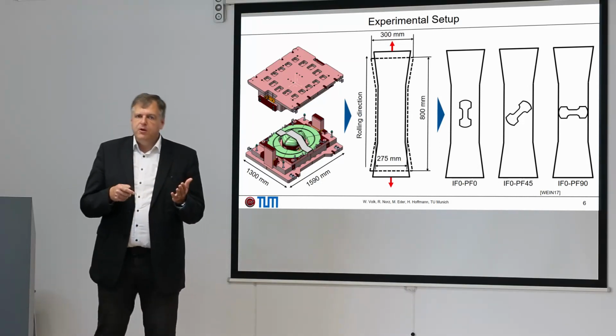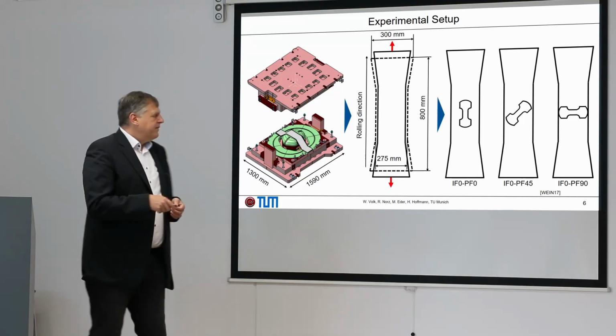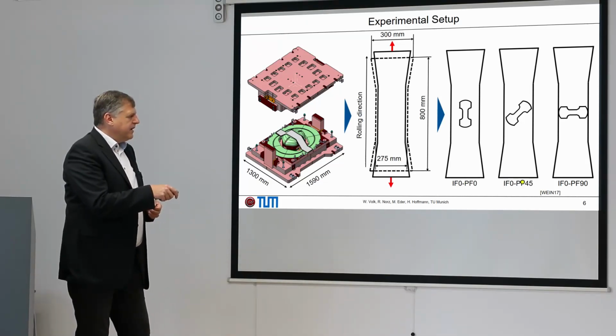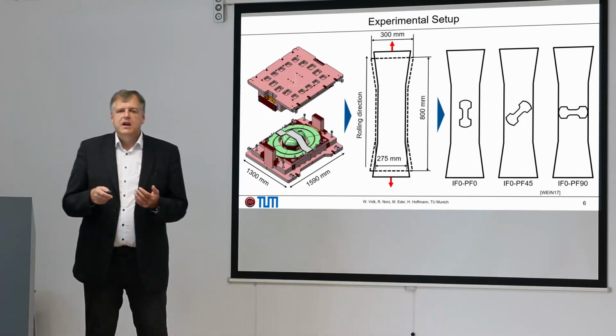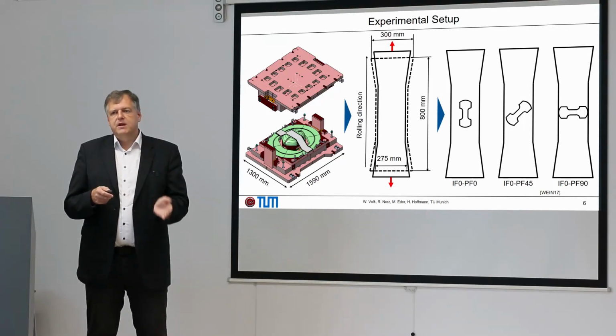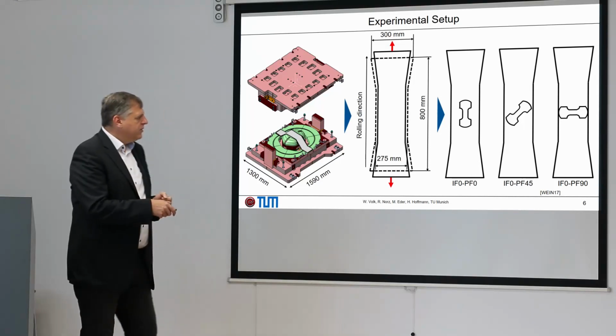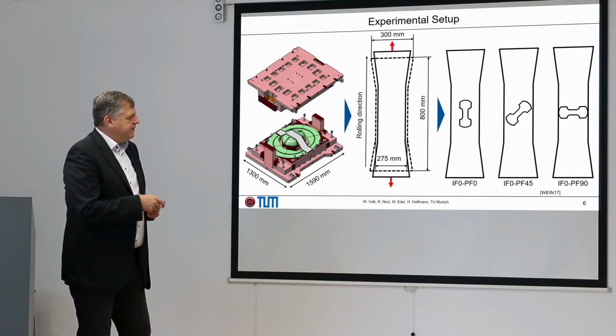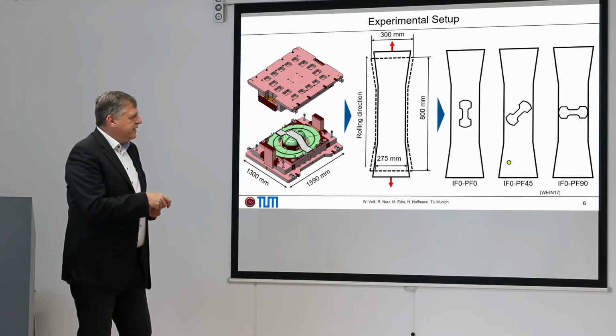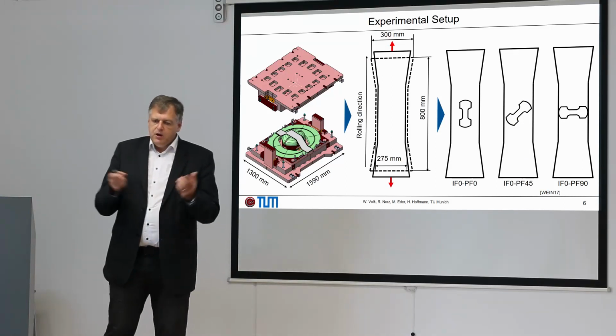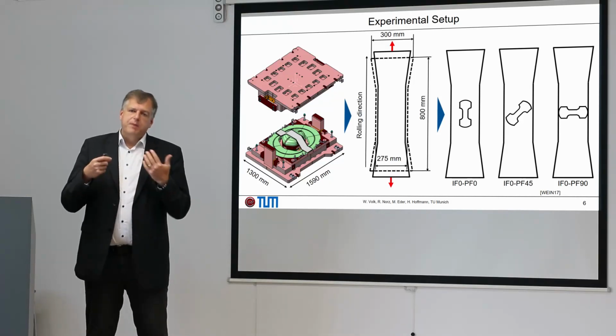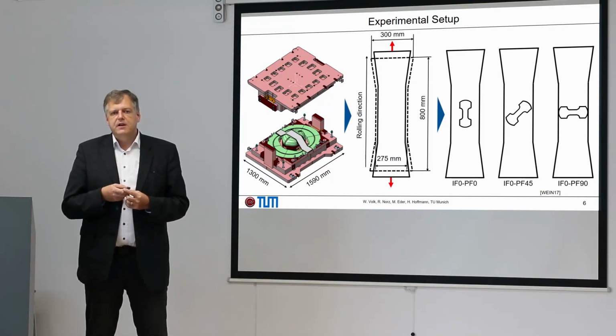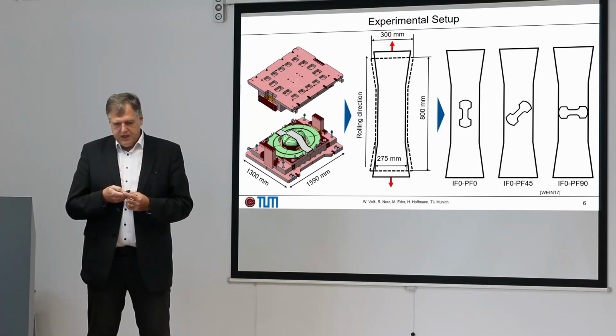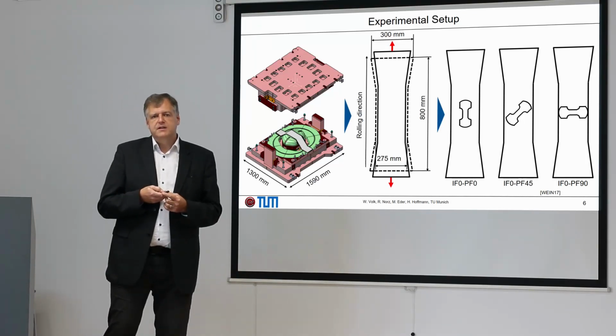We have an initial forming step and a post-forming step. And when there is now 0, 45, and 90 for simplicity, I just always mean with respect to the rolling direction. So IF0 PF45 means 0 degrees for the first step and 45 degrees with rolling direction for the second step. Okay, we didn't expect a big difference, but a remarkable difference, and performed the experiments. And then really a surprising effect came out.